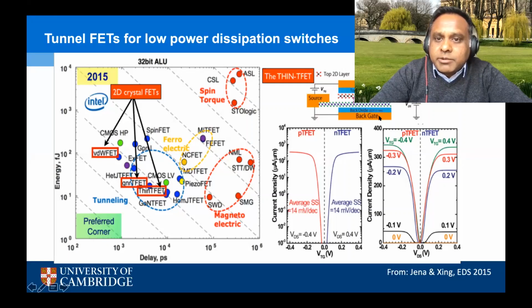And so they propose this type of device structure, which is simply having a P-type 2D semiconductor and an N-type 2D semiconductor sandwiched between two gate electrodes, and this should give rise to device characteristics that look like this. Achieving a good tunnel FET with 2D semiconductors has been difficult. In the previous slide, the schematic that I'd taken was from Ionescu's group at EPFL. They've recently published a paper where they've integrated, I think it's tungsten diselenide with tin disulfide to realize a tunnel FET. So there is some work that's been coming out.